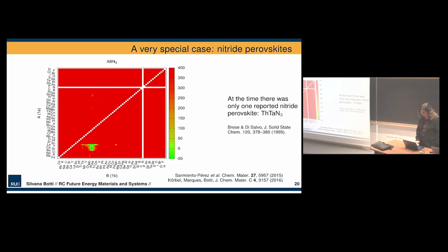And so that's why, if you look here, we see a region of green. This wouldn't be a cluster, it would be just some isolated green spots if we had ordered the chemical elements A and B using the atomic number. This is in milli-electron volts per atom, so the scale is not shown here. And you see that there is negative. So what does it mean if the distance to the convex hull is negative?